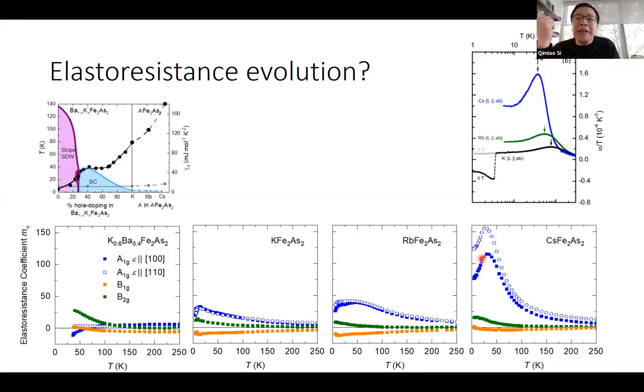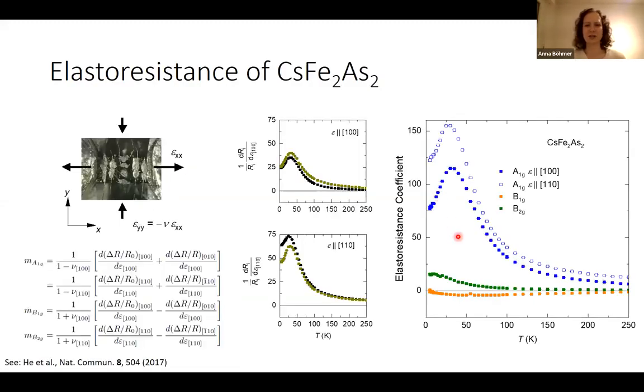And from an experimental perspective, what's the subtlety in the assignment of the measured quantity to these various components? Well, there are different experimental challenges. The challenge here is that one component is small, so to get it out accurately is not so easy. What you do in practice is you measure two directions and take a difference. And then it depends on misalignments, maybe. That's one challenge. We use a single sample for the two directions. That helps a bit. It doesn't affect the conclusion that the A1G component is dominant. It makes it difficult to get the exact temperature dependence and the exact size of the subdominant contributions.